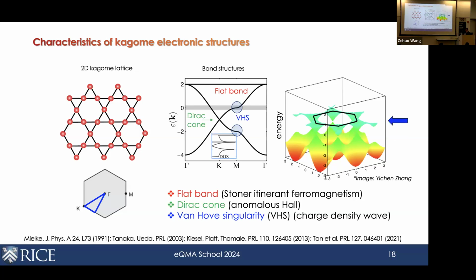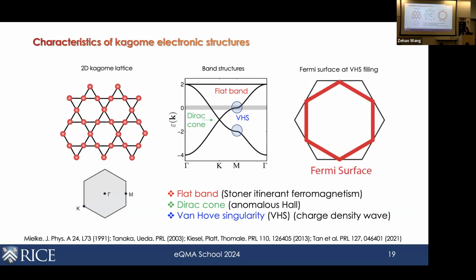And the interesting thing associated with this that's been known is that your Fermi surface at that chemical potential looks like this, which in this idealized picture is a hexagon. And when you have this kind of Fermi surface, then there are 3 pairs of parallel sheets of the Fermi surface that would be unstable against nesting across this wave vector. And so theoretically, this would give rise to, for example, a charge density wave that is 2 by 2. So it flows from this side to this side. And there are 3 of these parallel sheets of Fermi surface in this regime.